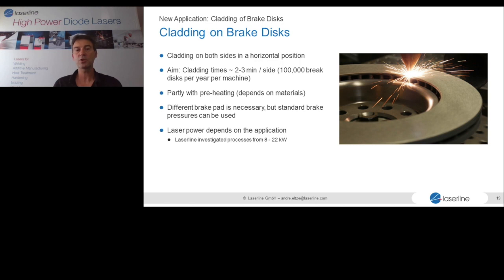And some simple calculations show then, because we have to clad the brake disc from both sides with at least two layers each side, that we have something like 2 to 3 minutes cladding time for each side, because in the following, the brake disc is also machined, grinded to remove the rough surface and get a nice shiny surface. So the development we did was aiming at 2 to 3 minutes per side, which requires quite a lot of laser power. So the development we did in our Laserline lab in Koblenz was based on laser power between 8 and 22 kilowatt.